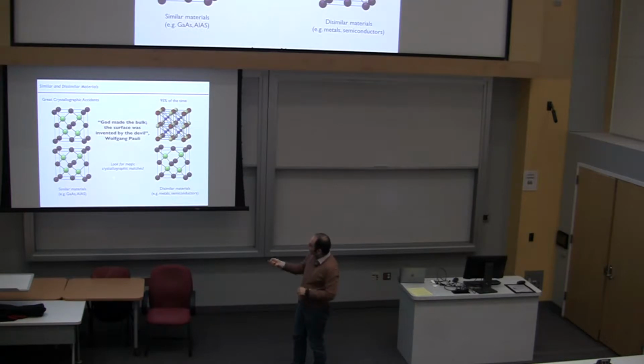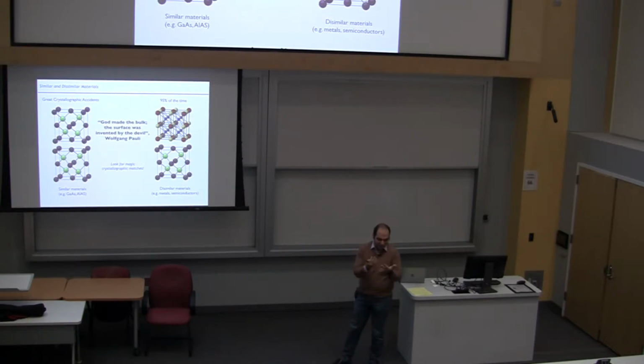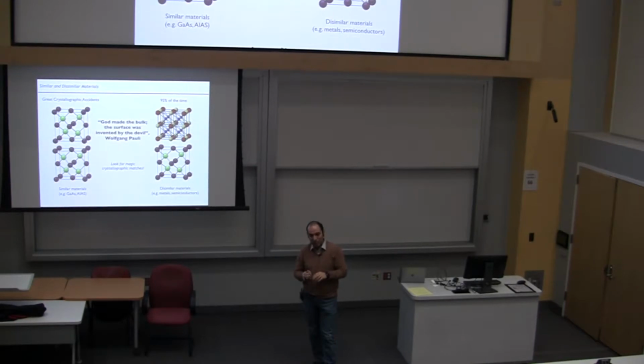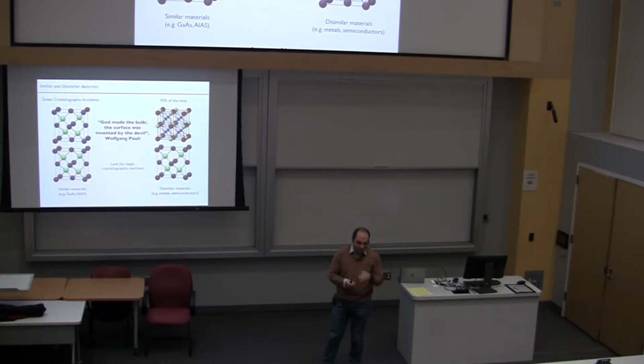But this is a quote from Pauli that says, God made the bulk, and the surface was invented by the devil, right? And it's kind of true that interfaces have their own nature. If somebody tells you gallium arsenide, you have to think about two things: the bulk of gallium arsenide and the surface of gallium arsenide. There are two different things. Like indium arsenide, I will show you later, is a semiconductor. It has a band gap, like 0.37 eV, but the surface is conducting. It has nothing to do with the bulk that is gapped, right?